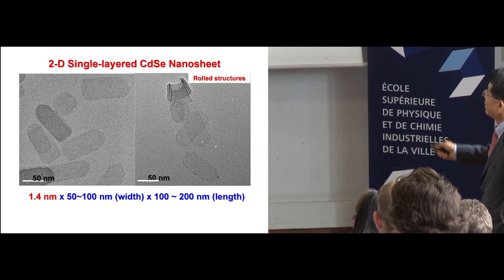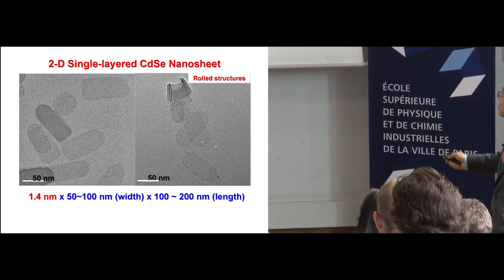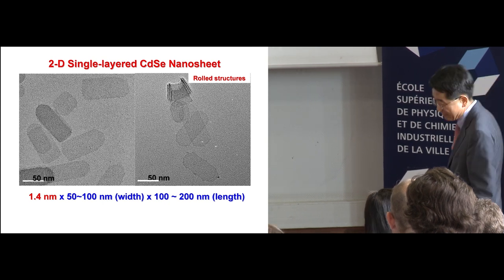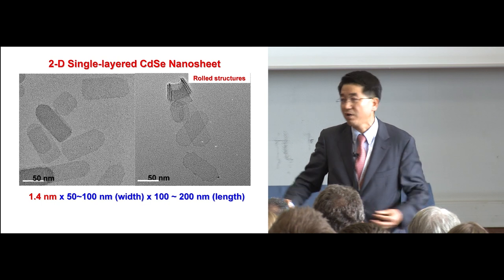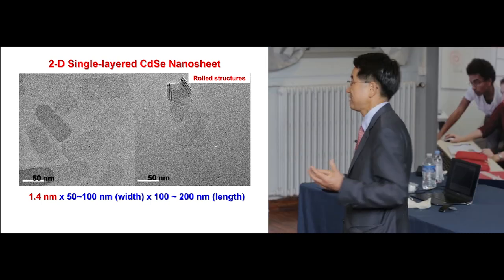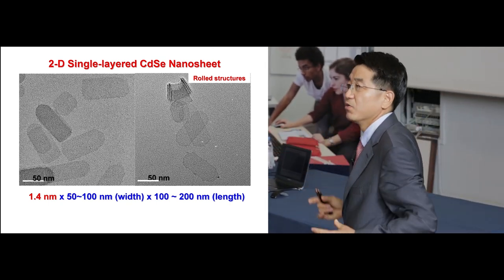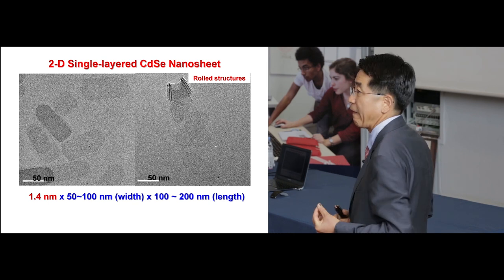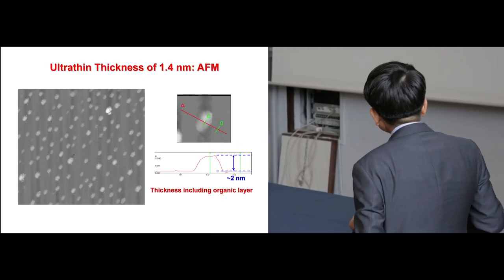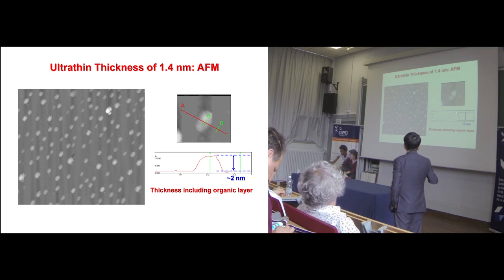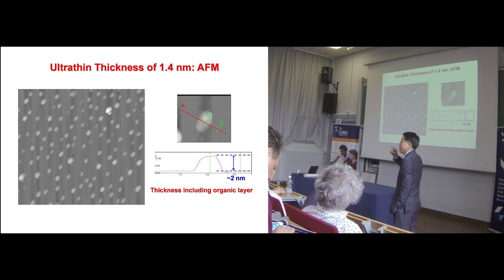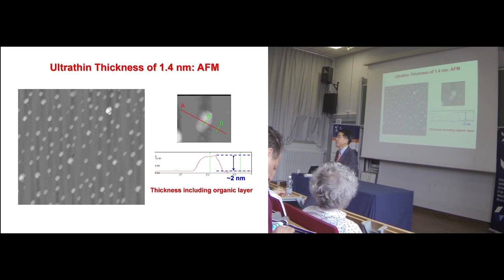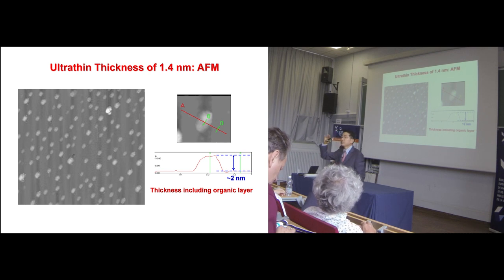And also we can get separated single nanoplate or nanosheet-like structures, okay? As you can see, thickness is 1.4 nanometer and this is the width. We still try to get larger dimensions for different kinds of applications, like FET, for example, but it's still very tough to make larger-dimension materials of a single nanoplate, okay? That was still pretty challenging. And when we took the AFM images, we can see that the height is 2 nanometers. So although the core CdSe thickness is 1.4 nanometer, the AFM can still see the organic layers too, right? So when you consider the octylamine or oleylamine layers, this is pretty much right.